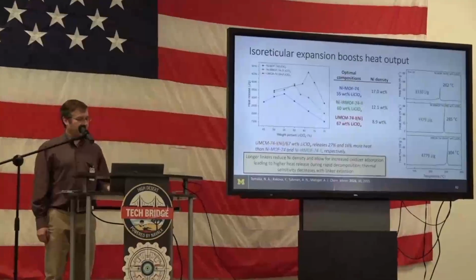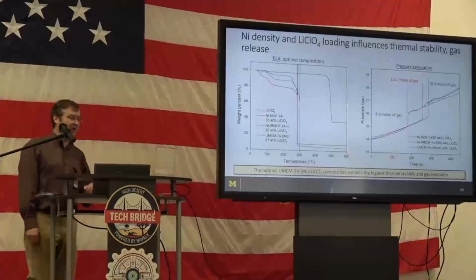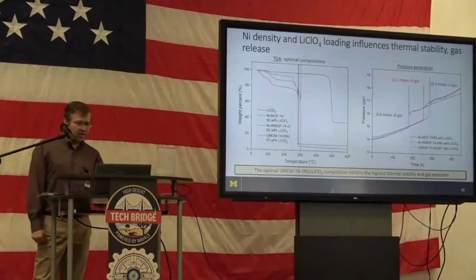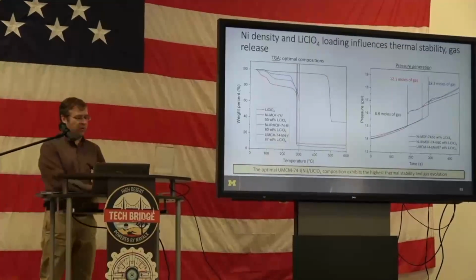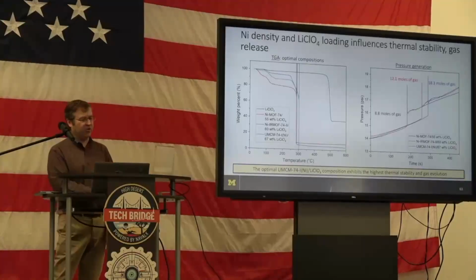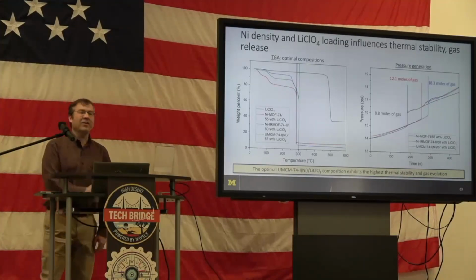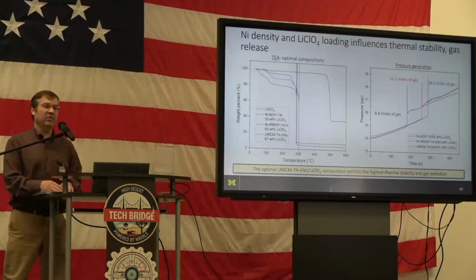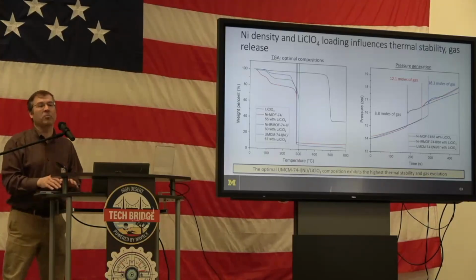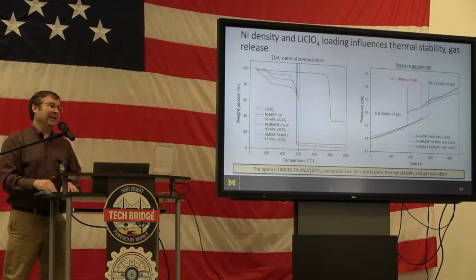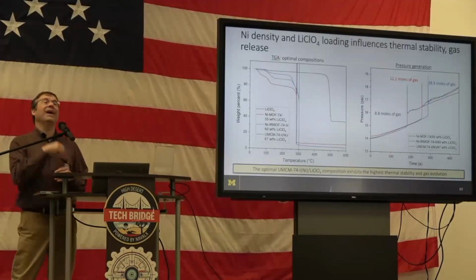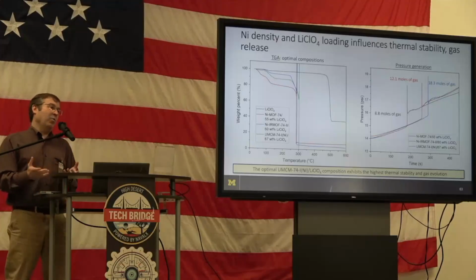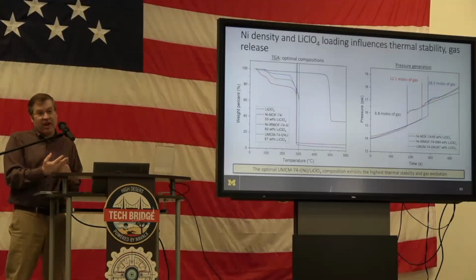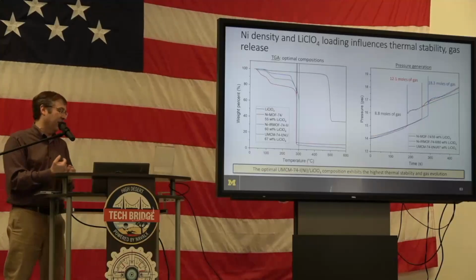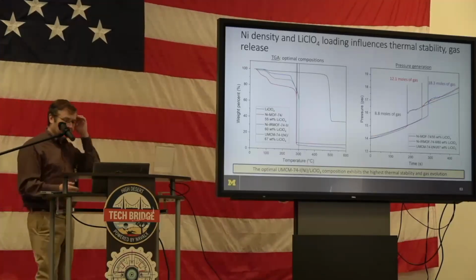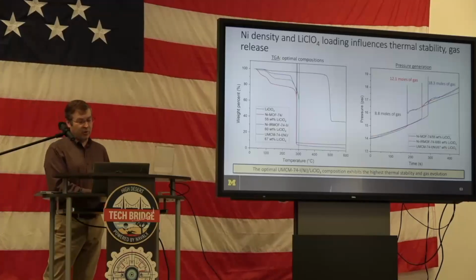We're also generating a lot of gas here, but I'll show you something that is maybe pretty surprising, which is from the TGA. This also shows up in the DSC. The highest performing composite, the one with the energetic linkers, is actually the most stable. So it goes off at a higher temperature by DSC and by TGA. Now, one possible reason, it does have a lower nickel content, so it could be that we have less catalyst, but there could be some other reasons too. It's the one that gives us also the greatest gas generation.